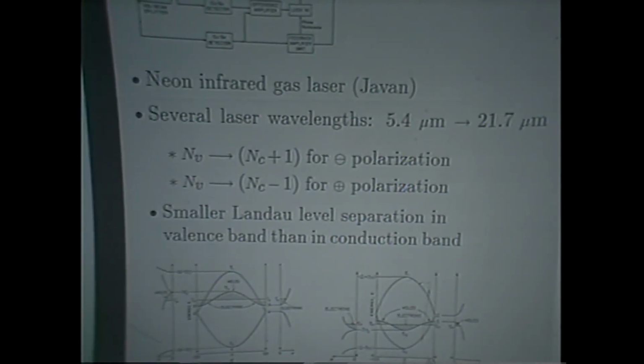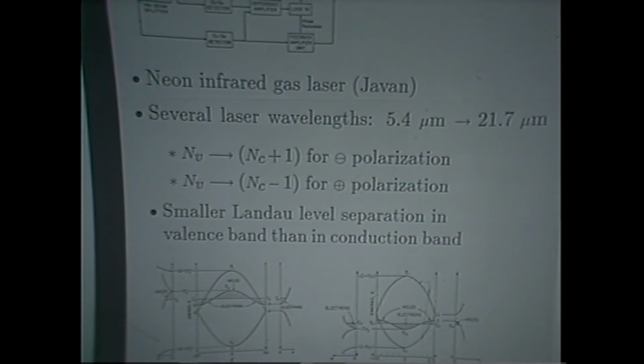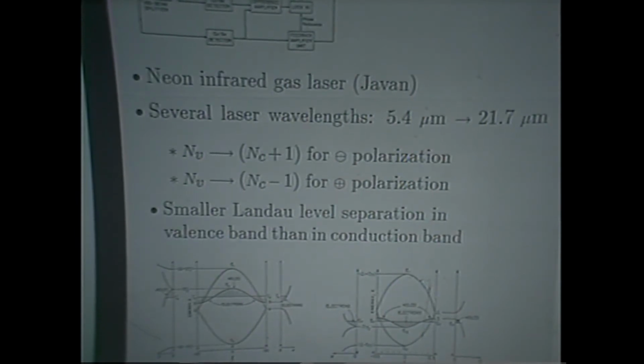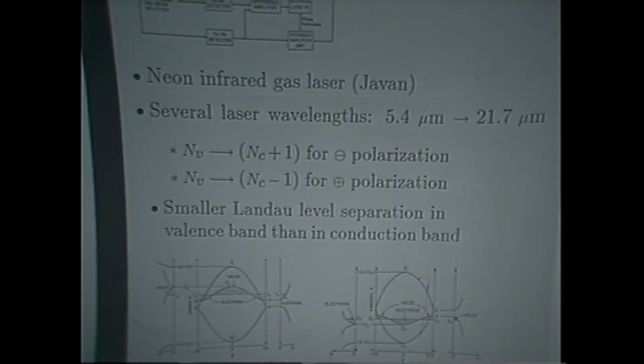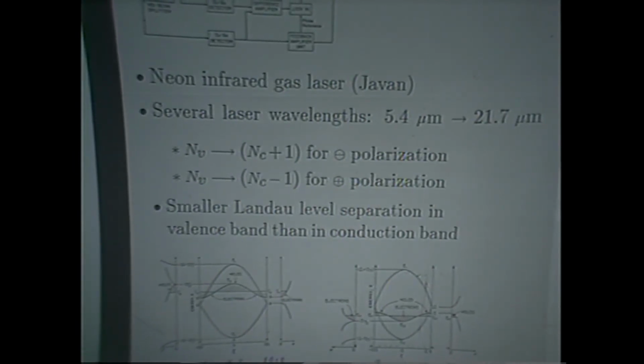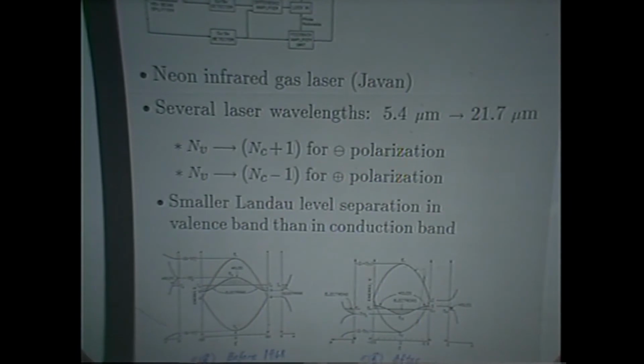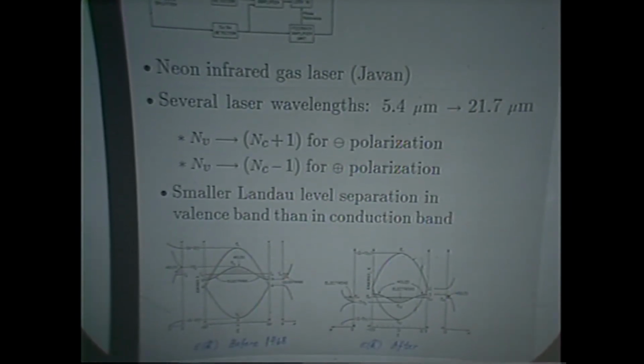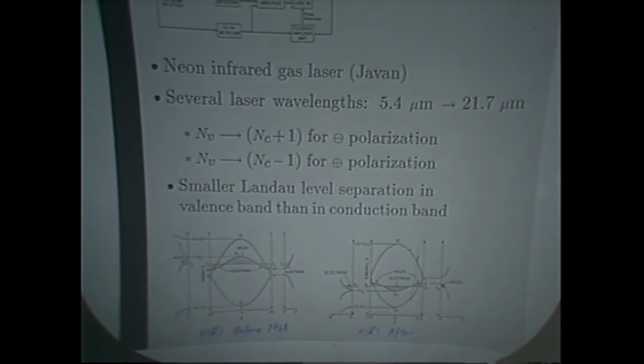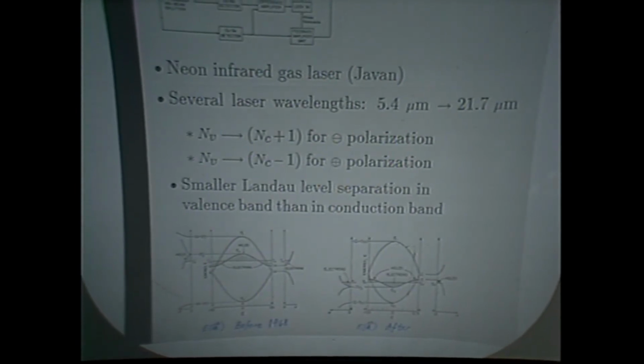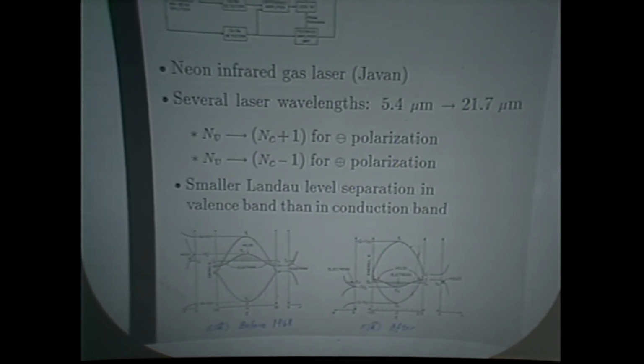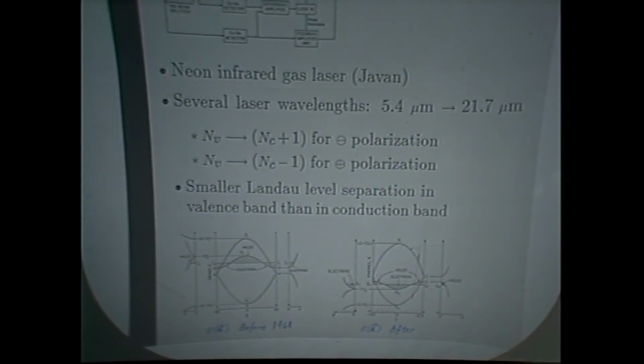See, for this experiment, we needed right and left circularly polarized light. We didn't have it with the old setup. It was difficult with the intensities needed to produce that. And with the laser, we were able to get this kind of intensity. And this was really intended to be an innocent experiment. It didn't turn out to be so innocent, but it was intended to be innocent. And the very first thing that showed up after we got results, and that was about 3 years after the start of the experiment, and the first results proved